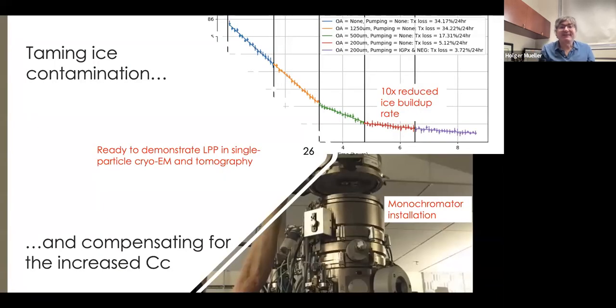We've also tamed the ice contamination of the Titan by additional pumping stages and by using an objective aperture that is large enough to not affect the imaging properties of the microscope, but small enough to block most of the ice. And that has reduced the ice buildup rate about 10 times, where it's still not as good as in a Krios, but good enough for us to take data. And the final limitation was the increased chromatic aberration of our relay optics.